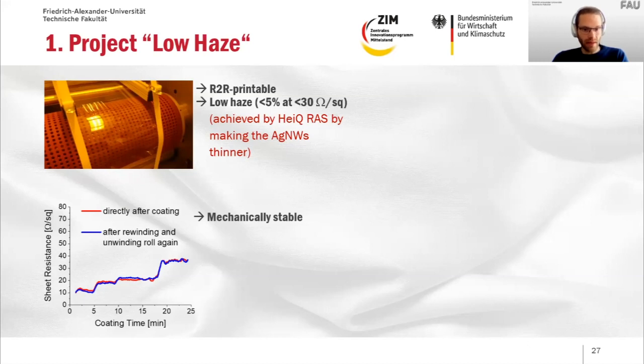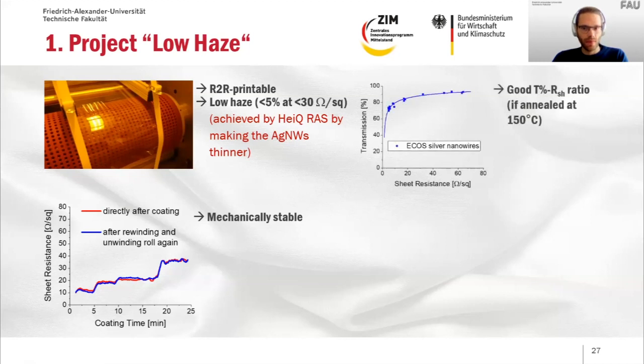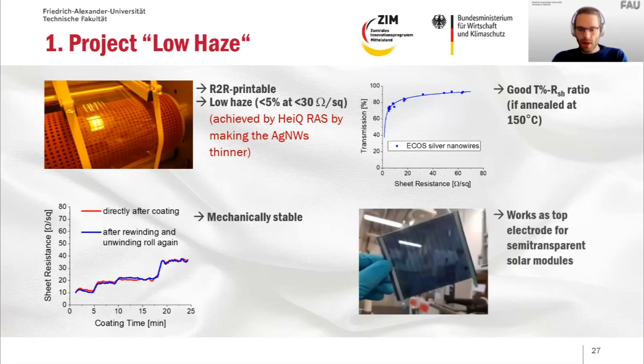These coatings were fairly mechanically stable, so we were able to unwind and rewind this roll several times without causing any changes in the sheet resistance, which is an important factor for manufacturing on a large scale. The sheet resistance transmission ratio was very good. We reached more than 80% transmission at less than 20 ohms per square sheet resistance as desired. The only drawback was that we needed to anneal it at 150 degrees to reach these values. So this could have been better. But we tried it in our solar modules as top electrode and it worked perfectly fine. So you can see one of these semi-transparent modules with ECOS top electrode.